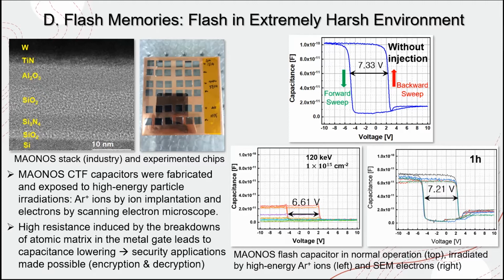The gate atomic matrix is severely broken, and a high parasitic resistance is introduced in series with the capacitor of the flash memory, and that reduces the effective capacitance. So the reduction in capacitance means difficulty in identifying the on and off state of the flash memory device, because the capacitance is linearly related with the drivability at an operation voltage, the read voltage. And the memory window shrinkage is also a critical issue when it comes to memory operation.